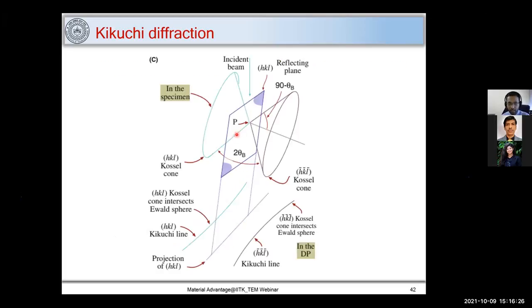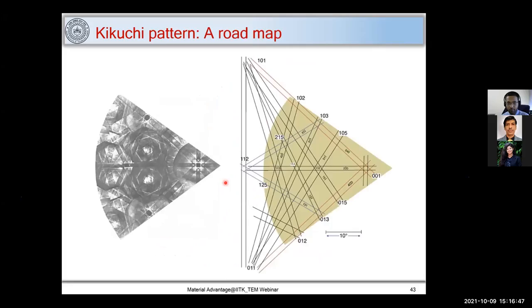And these are nothing but the loci of all such points, and these are nothing but a cone. When I image that on this image plane, when these cones intersect, this forms lines, and these are called Kikuchi lines. Now these lines will help us to identify the location of the planes also, but we'll be looking at it to tilt our sample. So you have a Kikuchi pattern, and for different crystal structures, you have different Kikuchi patterns, and this can be a roadmap.